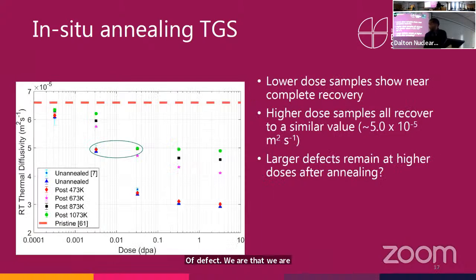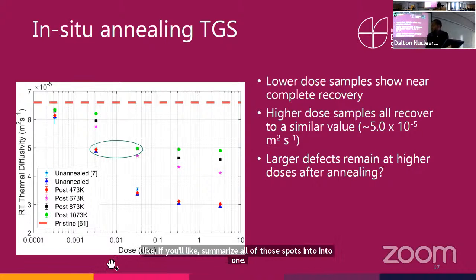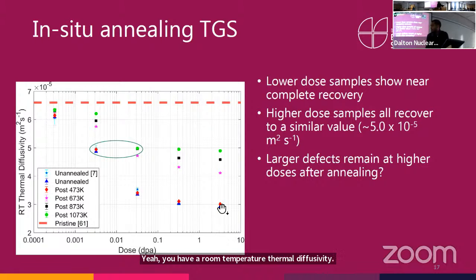And yeah, so if you summarize all of those plots into one, here you have your room temperature thermal diffusivity. For example, for a high dose, let's say 3.2 dpa, you start off here, and after annealing in several steps, you reach this maximum of 5e-5. For the low dose samples, you start off here, and then you recover your pristine diffusivity, which led us to think that obviously there are different types of defects, and there are some defects in the high dose samples that do not anneal off even at 1073 Kelvin.